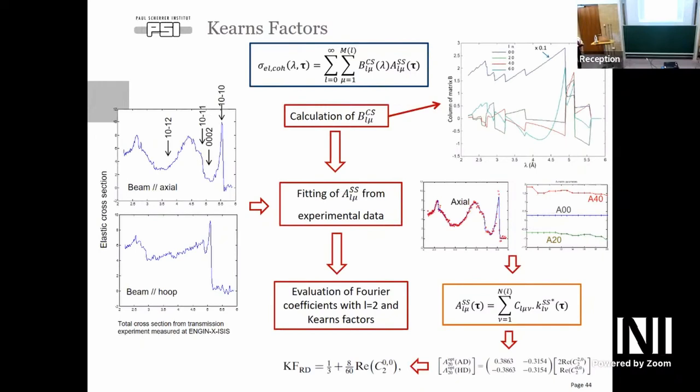If you have a thermal beam, if you have a cold beam, that will depend. The point is that it's an empirical rule for how far the noise is. Yes, you can have an approximation, but that also depends on your sample. If I measure a copper or a zirconium alloy, I will have a completely different signal to noise ratio.